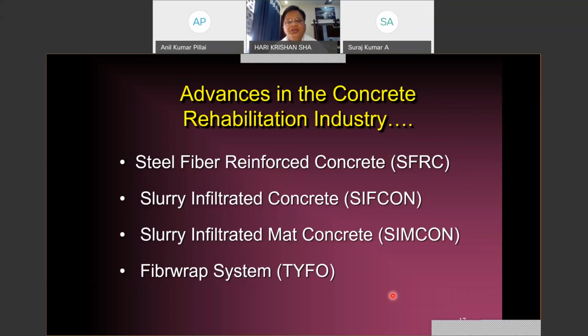Now you will find that SIFCON is basically a different material, and the methodology for manufacturing SIFCON is also different. In this method, we put steel fibers which may be up to 18 to 20% by volume of concrete. By increasing the percentage of steel fibers, there will be a tremendous increase in strength, whether in compression, tension, flexure, or shear. The methodology by which this material was developed was entirely different from that of steel fiber reinforced concrete.